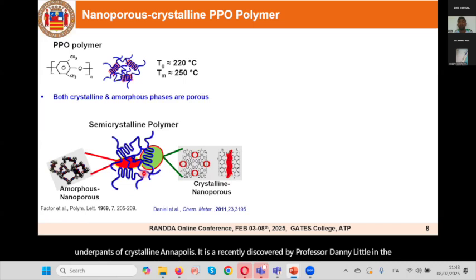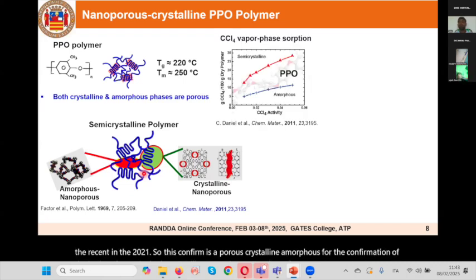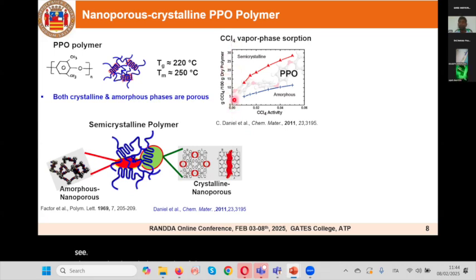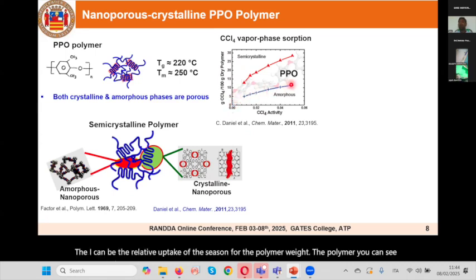For confirmation of the presence of porosity in the crystalline and amorphous phases, Professor Daniel and colleagues recently studied the vapor phase sorption of CCl4 at different activities, at different relative pressures. You can see the relative uptake of CCl4 with respect to the polymer weight. The pure amorphous PPO polymer also shows some sorption, nearly 8% by weight, whereas the PPO semi-crystalline polymer is much higher than the amorphous. So that confirms PPO is porous in both crystalline and amorphous phases. That is the first confirmation.